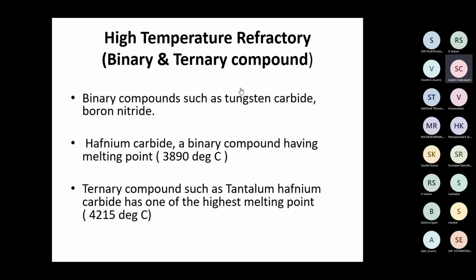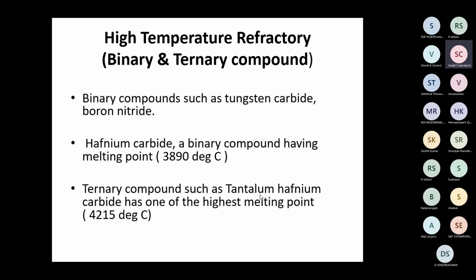So, high temperature refractory: binary, ternary refractory. This is a high temperature refractory. Binary compounds such as tungsten carbide, boron nitride, hafnium carbide, a binary compound having a very high melting point, 3890 degrees centigrade. Ternary compounds such as tantalum hafnium carbides have one of the highest melting points, 4215 degrees centigrade.